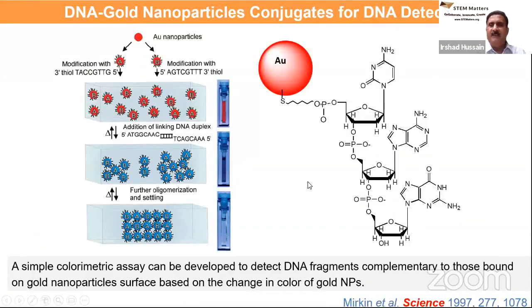So here are some of the applications of these gold nanoparticles based on colorimetric detection. Professor Chad Mirkin, some of you would know, is among the pioneers who used these gold nanoparticles and exploited their optical properties to introduce a variety of colorimetric methods for the detection of a variety of biomolecules. In this case, they conjugated gold nanoparticles, about 15 nanometer, with DNA molecules that were end functionalized with thiol, for example. Simply by incubating gold nanoparticles with thiol functionalized DNA, you can prepare these bioconjugates.